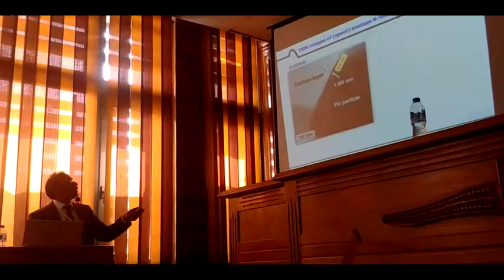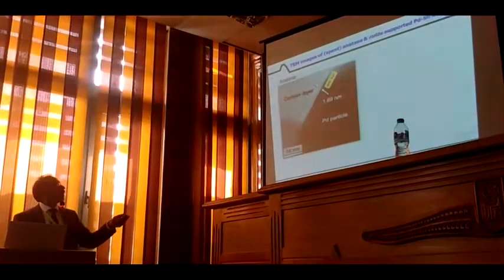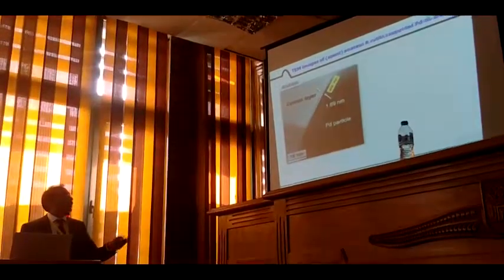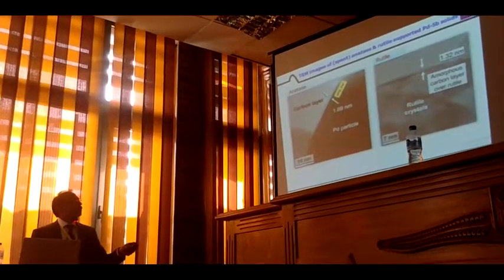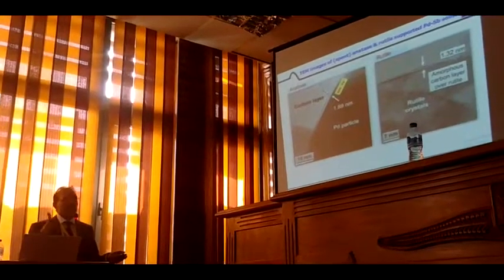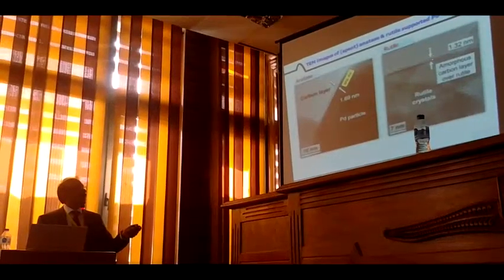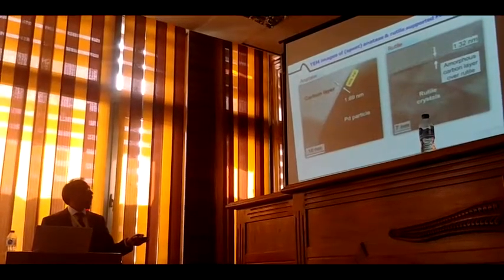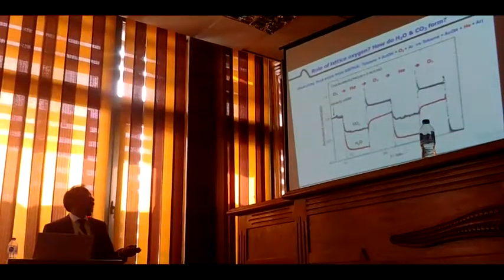In this case, there is a carbon deposition directly on the palladium particle. If you estimate the carbon layer thickness, it accounts to 1.69 nanometers. And if you see the non-deactivating catalyst, the carbon deposition is preferentially going to the rutile crystals on the support, not blocking palladium sites. This is one reason why rutile is better than anatase. And also, the carbon layer thickness is 1.3 nanometers against 1.69 in this case. So this also matters. There are some isotopic experiments, but I will skip this.